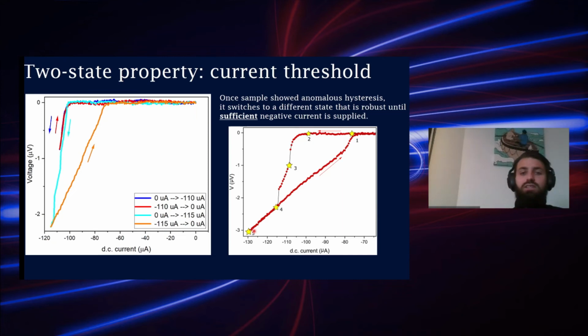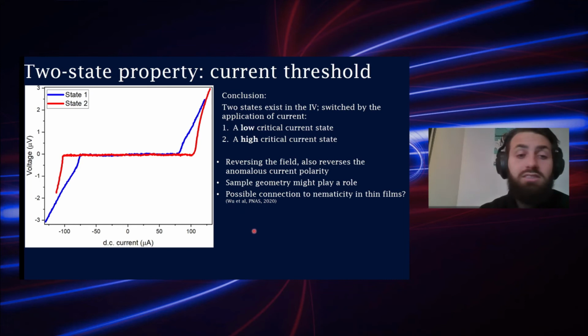So instead of thinking of it as an anomalous hysteresis, it's actually a two-state property that we reveal using these in-plane fields. There's one state, the low critical current state, highlighted in blue, and the high critical current state, highlighted in red. You can switch between them by application of current.